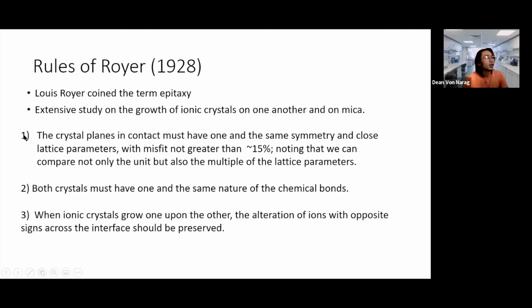So here are key set of rules. For the first one, the crystal planes in contact must have one and the same symmetry and close lattice parameters with misfit not greater than approximately 15%. Noting that we can compare not only the unit but also the multiple of the lattice parameters.